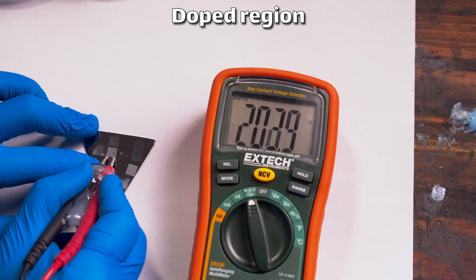The more definitive test, which is honestly what convinced me that something is happening here, is known as the hot probe test. This is very simple: you take your multimeter probes, probe the surface, and heat up one of the probes with a soldering iron or in my case a hot glue gun. When you heat up one of the probes you will see a change in voltage, either positive or negative depending on what type the silicon wafer is.